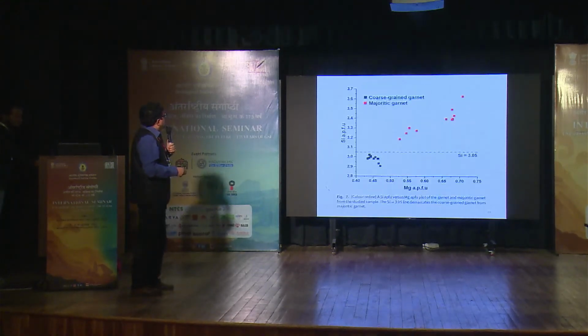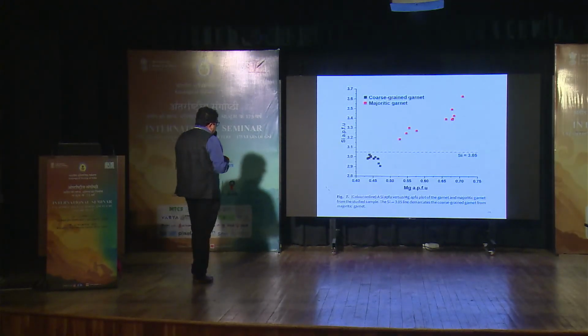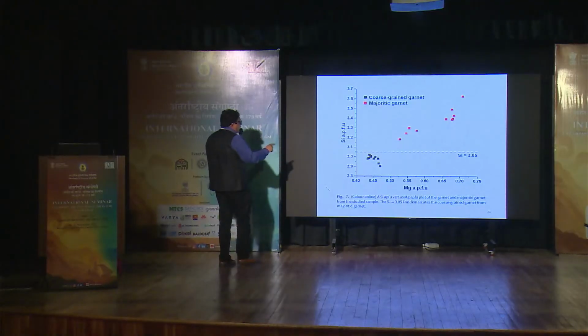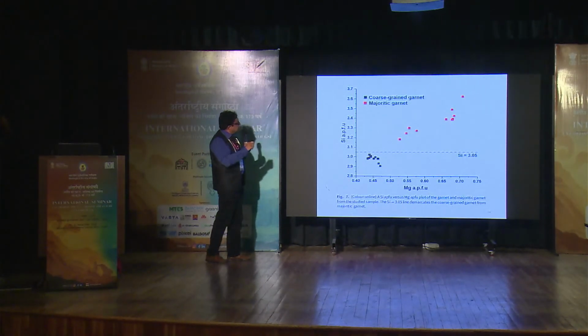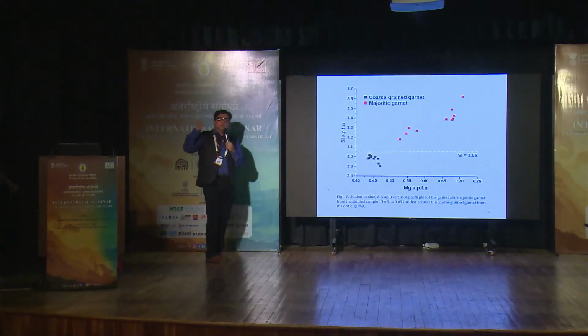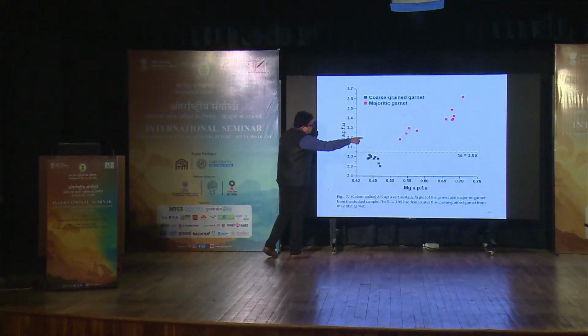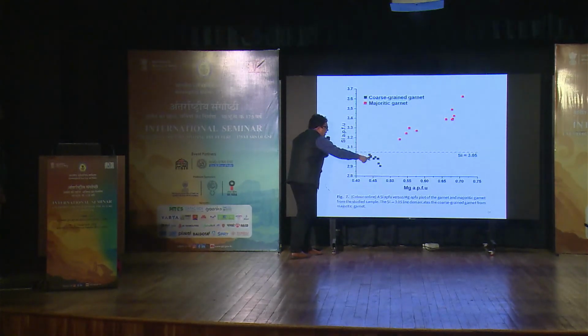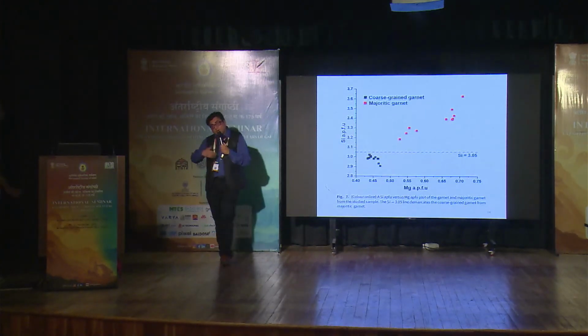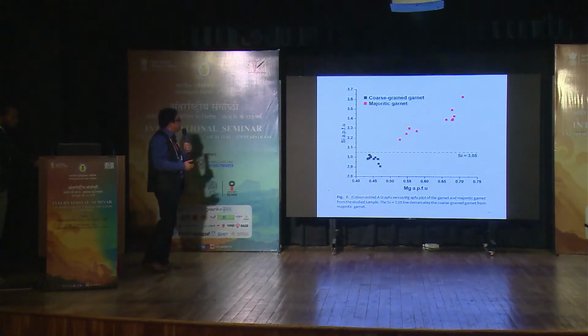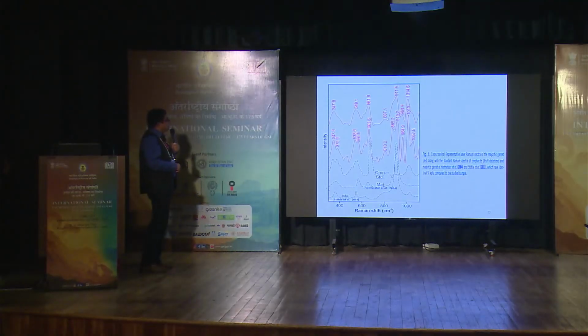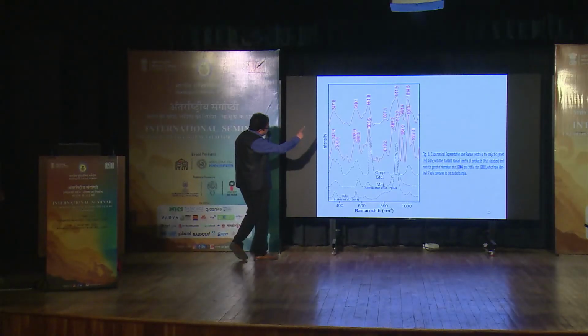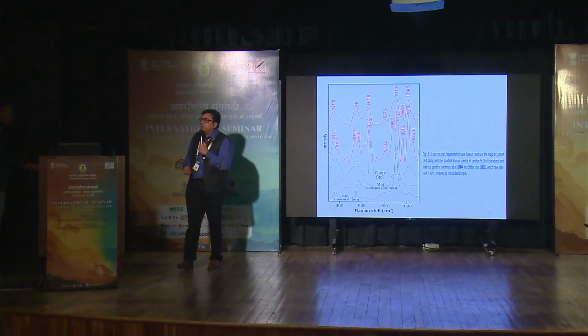Next one. Now, you can distinguish chemically based on EPMA data, based on their silicon and magnesium cationic proportions, between normal garnet and majorite. I mentioned the high silica content in majorite. It beautifully brings out that silicon 3.05 is the cutoff. This is the normal garnet composition in my eclogite, and these are the majoritic garnet compositions. You can discriminate between them very easily. Next one. Now we have also done Raman spectroscopy to reconfirm whether we really have a majorite or not, which matches very well with the majorite data available in the literature.